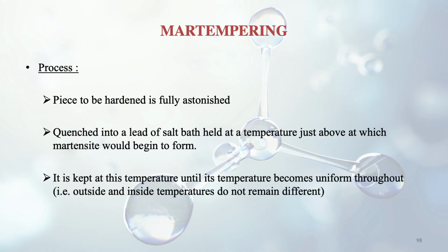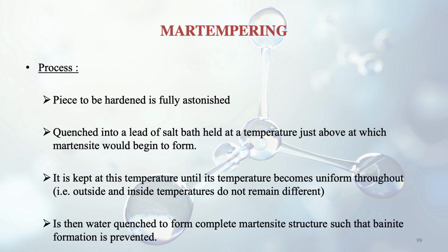It is kept at this temperature until its temperature becomes uniform throughout. So we keep it at this temperature for a certain time, so that every portion of the specimen has a uniform temperature, whether outside or inside. Then it is water quenched to form complete martensite, such that bainite formation is prevented. So this is the difference: here water quenching is taking place, and that's why no bainite forms and only martensite forms.